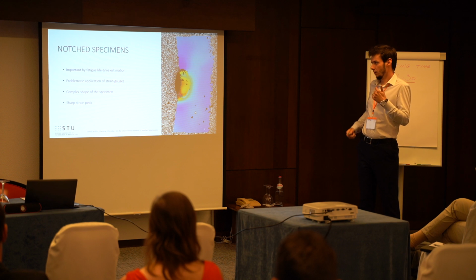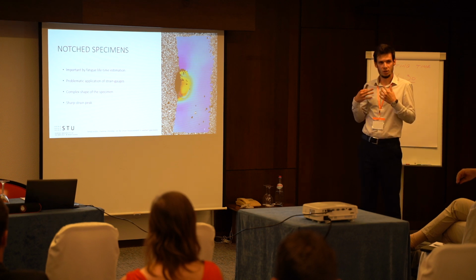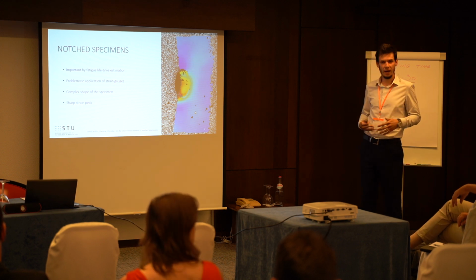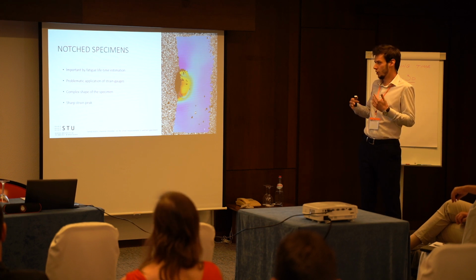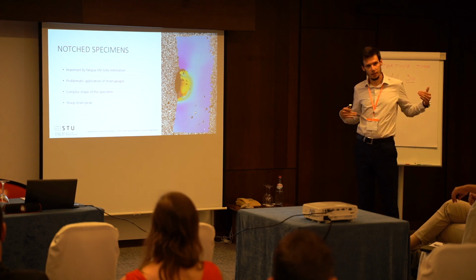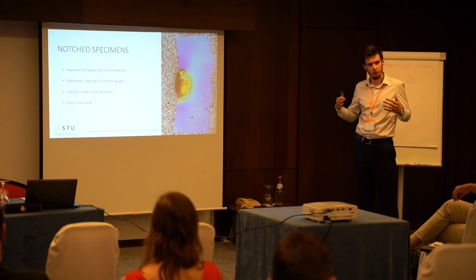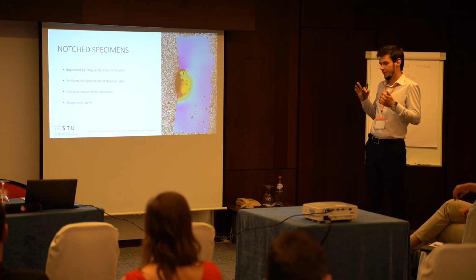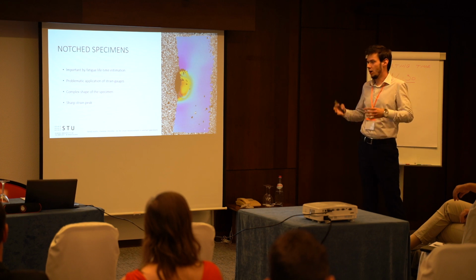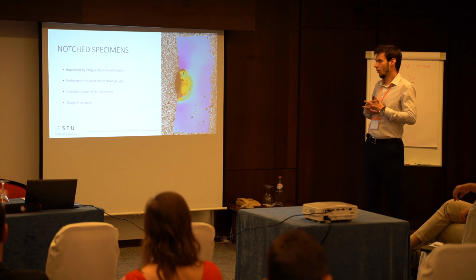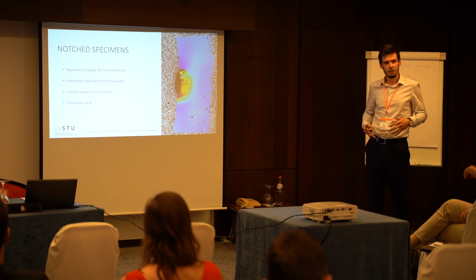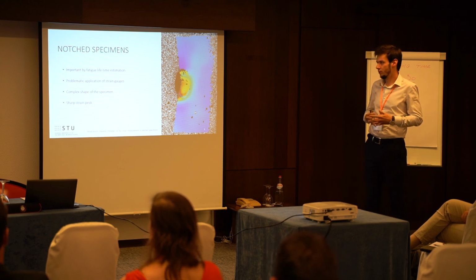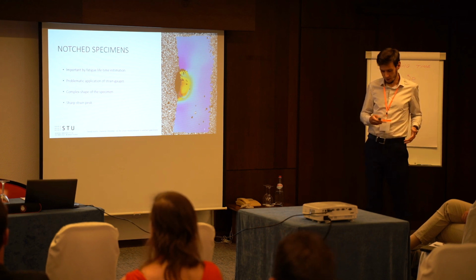This is problematic with strain gauges because of the complex shape of the specimen, or sharp strain peaks, which would be averaged through the length of the strain gauge. Therefore all of the optical methods come to mind, for example photoelasticimetry, ESPI, or digital image correlation.